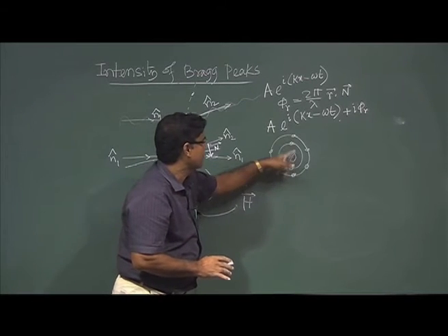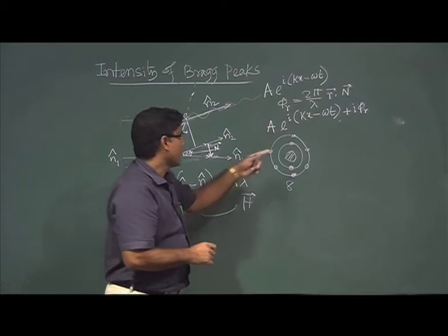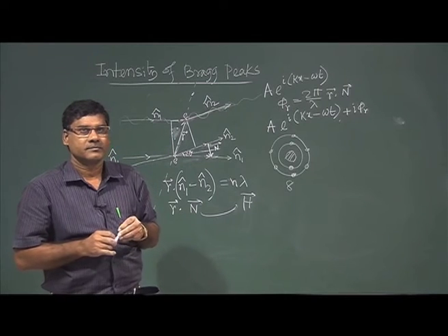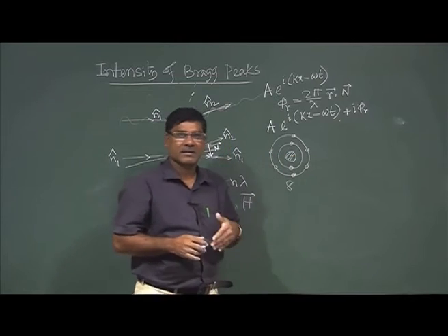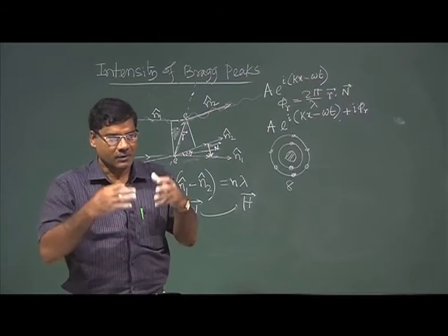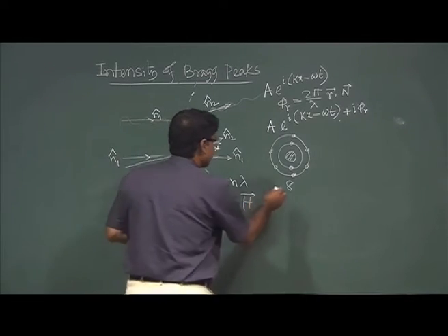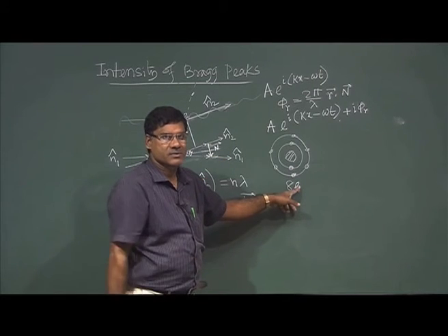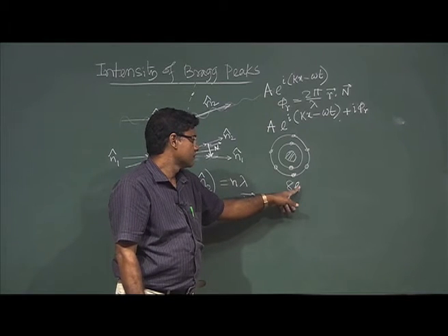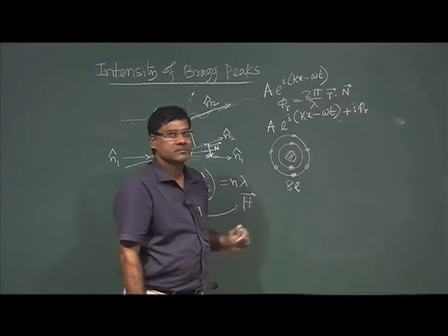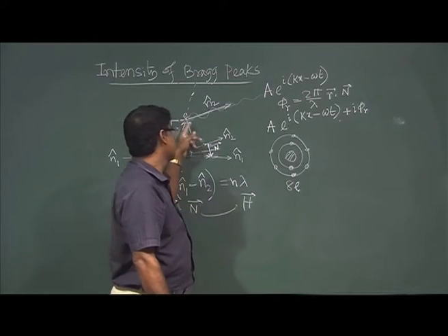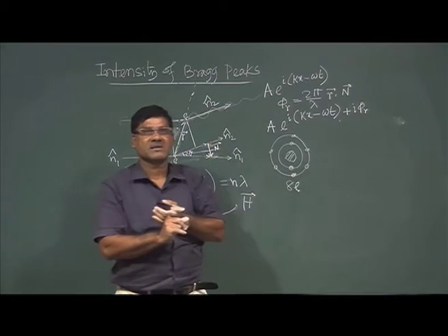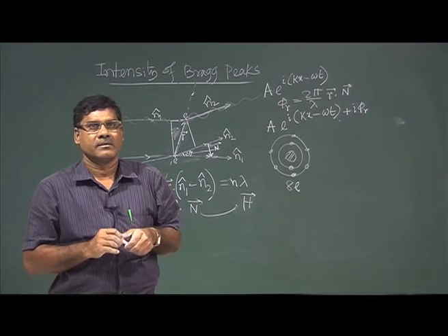It cannot be single, right? Say here I have taken 8 electrons. So from 1 electron, whatever the scattering strength, it has 8 electrons. So the total scattering strength, or total amplitude, cannot be 8 times of E, right. From a single electron, whatever amplitude I am getting, when it scatters from 8 electrons, it cannot be 8 times this single one, okay, because of this there will be phase differences and there will be an interference effect, and the resultant amplitude or intensity will be different, okay.